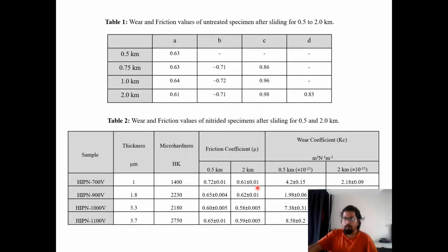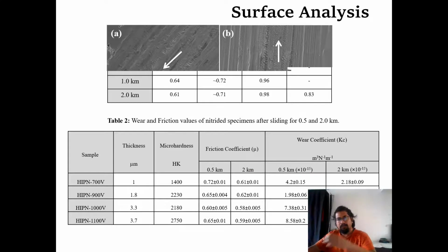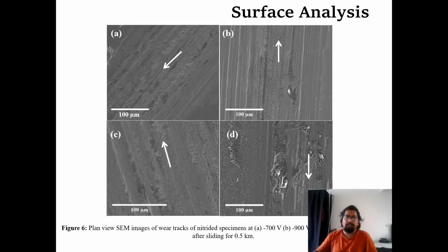And the same goes for the wear coefficient as well. We can see that for the 700 and 900 volt it was very low, and then it starts increasing for 1000 and 1100 volt. The SEM surface analysis basically depicts the same thing the values say, and we can see that the 700 and 900 volt surface was hardly damaged when compared to the 1000 and 1100 volt.